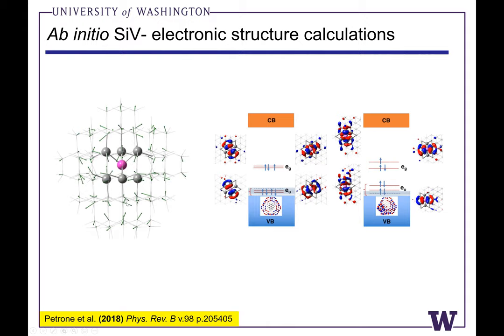And we mentioned to Zhaosong that we had made these silicon split vacancy point defects, and we asked them if they could calculate the pressure dependence of the HOMO-LUMO transition of these defects for us to compare with experiments. We had made experimental measurements of the pressure dependent shift of the zero phonon line luminescence from this defect. And we did a double blind experiment where we told them we had the data, but we didn't tell them what the slope was. We really wanted to kick the tires on their DFT code to see if it worked.